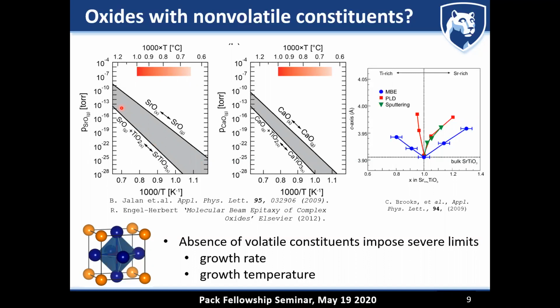And what happens now is that the stoichiometry is going to be determined by how much strontium and titanium flux, or in this case, calcium and titanium flux you're going to supply. And what people have realized, which is shown here, is that it is really, really hard to hit this perfect flux ratio in which you're going to get a stoichiometric composition. Anytime you're deviating from this ideal stoichiometric composition, you're going to see an expansion in your lattice parameter, which is shown here.